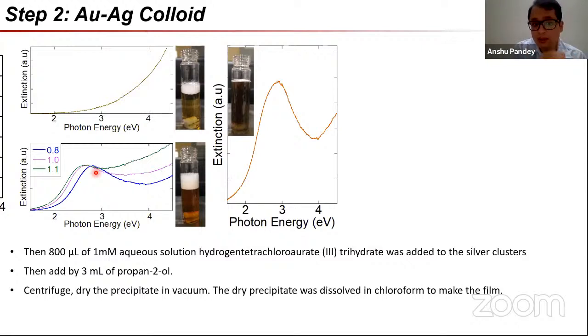Even if you believe that it must be doing that, then also there's a slight issue, because you see that there is no evidence that this material is going into a lossless state. This is actually an eminently lossy material still. It has all the regular features which a gold silver colloid should have. It has the gold plasmon resonance, and it has the additive spectrum of whatever the silver spectrum is. There's no change in it beyond.